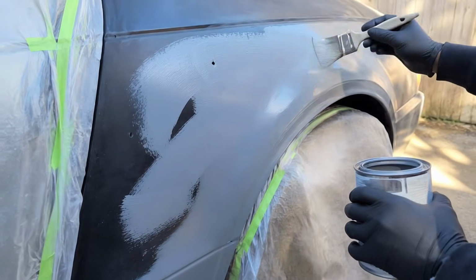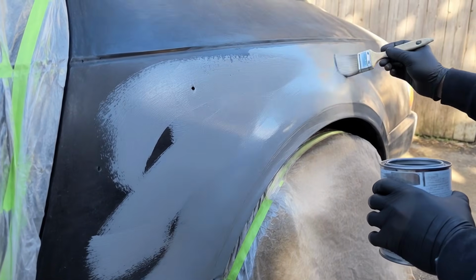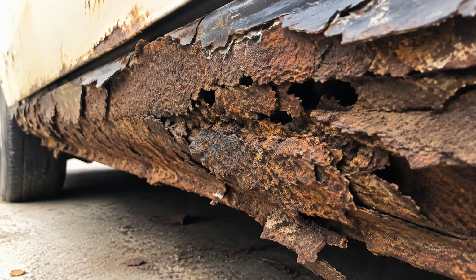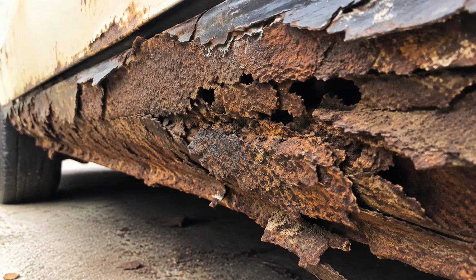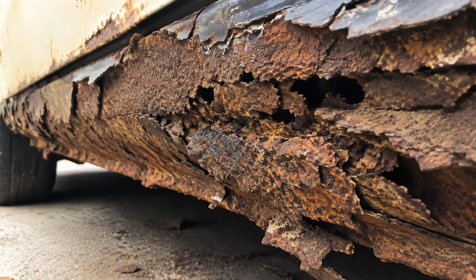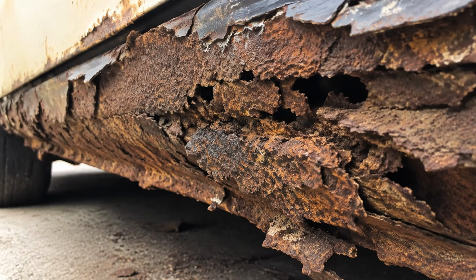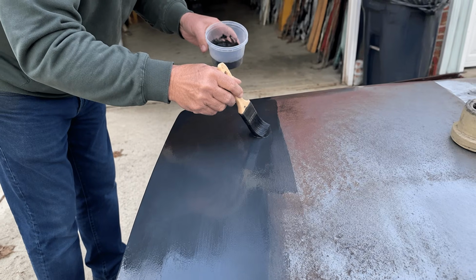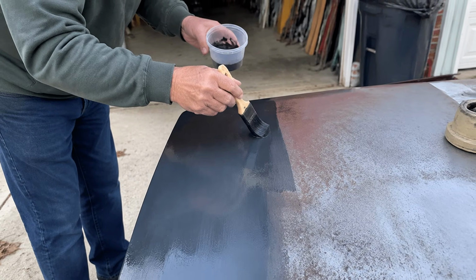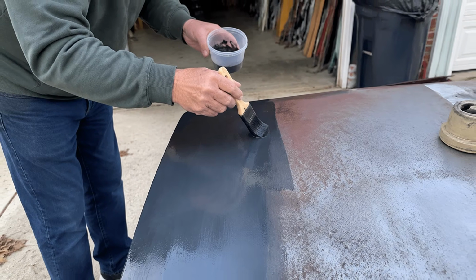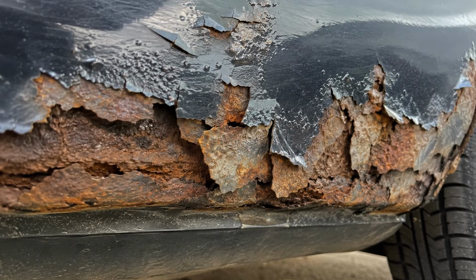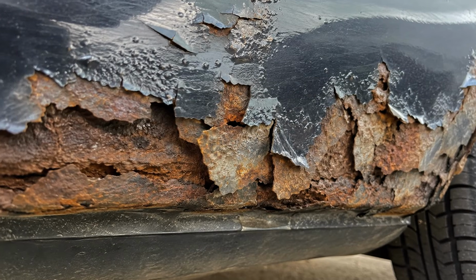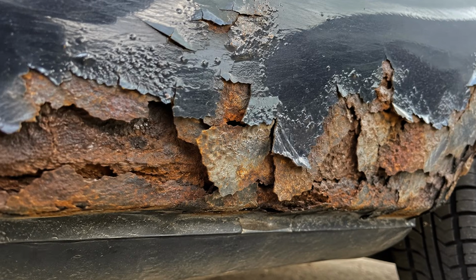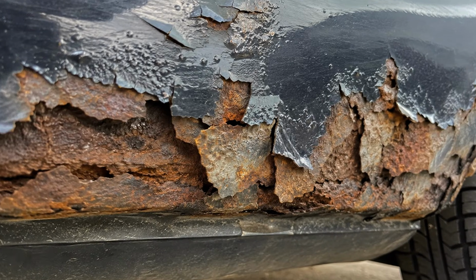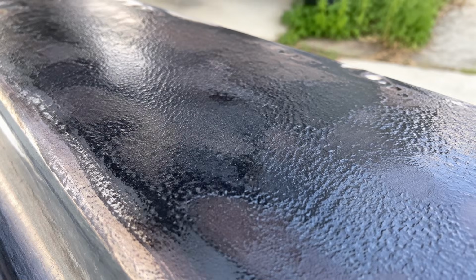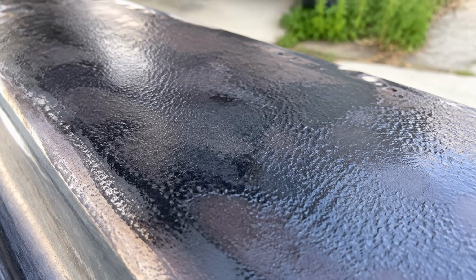What it does not do is remove rust, and it does not work miracles on thick, crusty scale, and it's close to useless on metal that's soaked in road salt. On a light, pitted surface, brushed on clean, it's a genuinely useful tool. On a flaking, scaly mess, it'll skin over the top and leave the active rust working away underneath. And now, you're right back to painting over a fire.